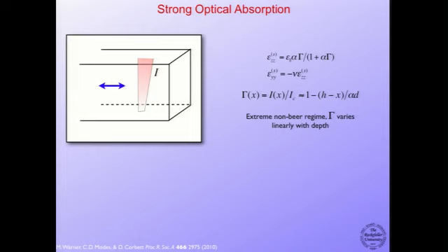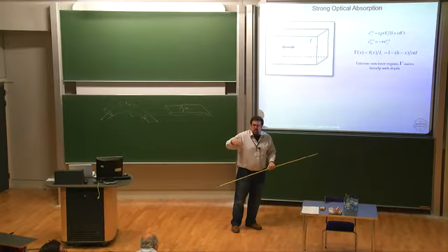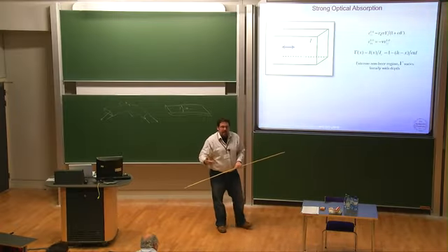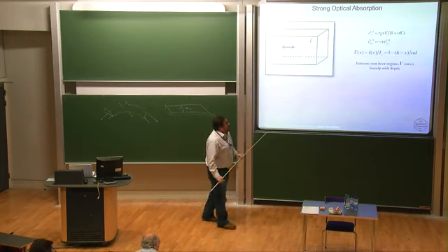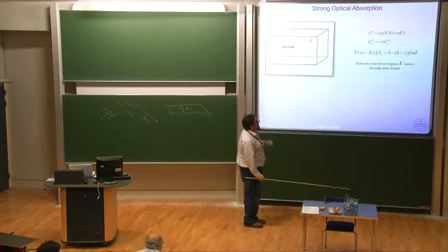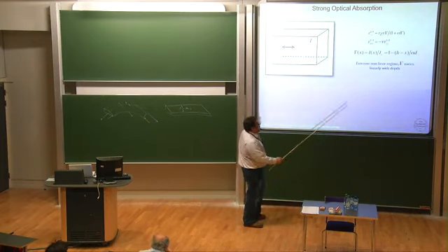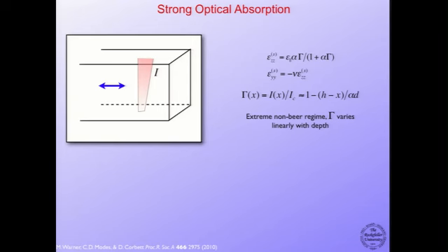So if the material absorbs much more strongly, you can photo-bleach it. The absorbers, the little azobenzene molecules, can all get used up, right? So at some layer, all of them have now bent, and that area will no longer absorb any light for any active purpose. And if you do that, you have to modulate the intensity as a function of the depth.